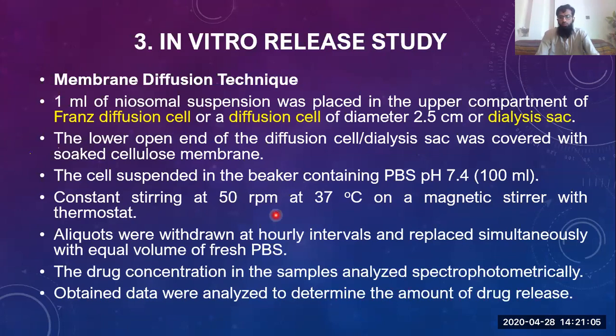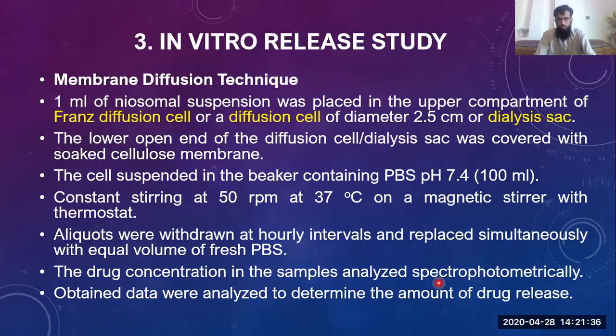We withdraw samples and replace them with an equal volume of fresh phosphate buffer. We then analyze the drug concentration spectrophotometrically to find the amount of drug released. From the data obtained, we find the mechanism of drug release — whether it is dissolution-controlled, diffusion-controlled, concentration-dependent, or concentration-independent — by applying kinetic models.